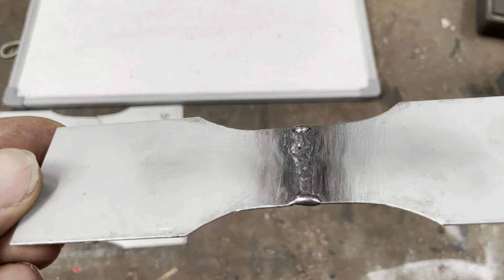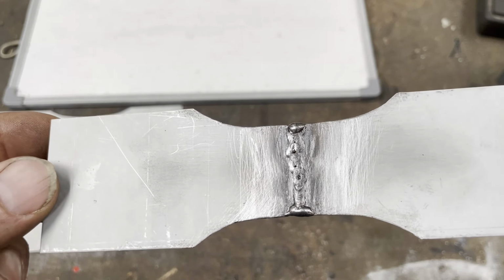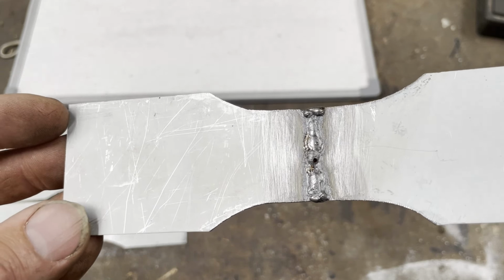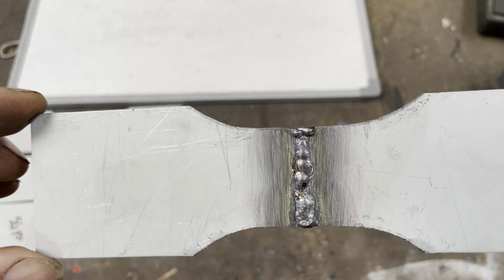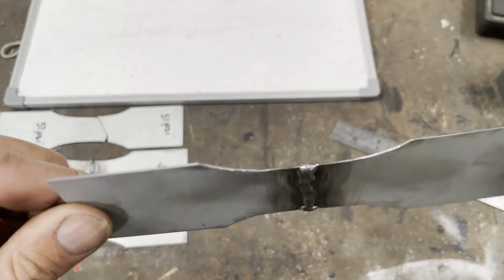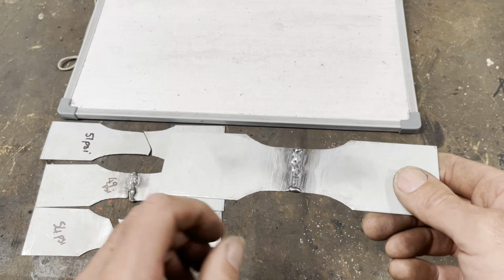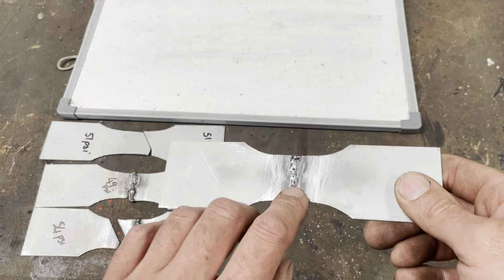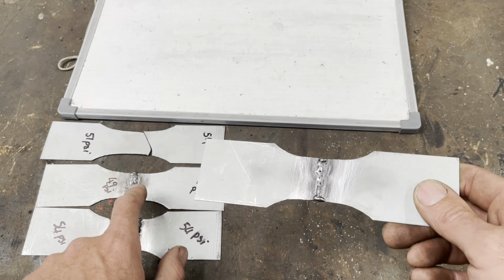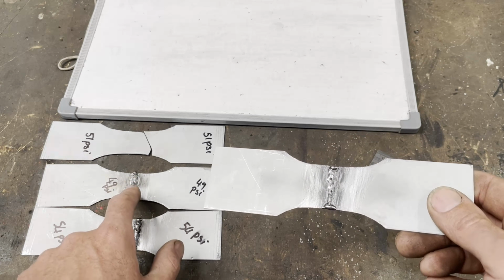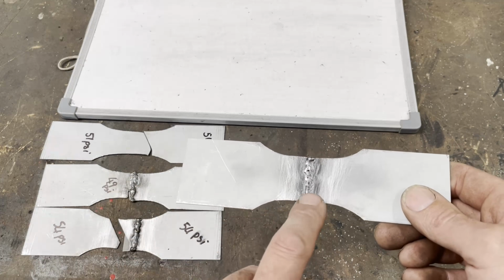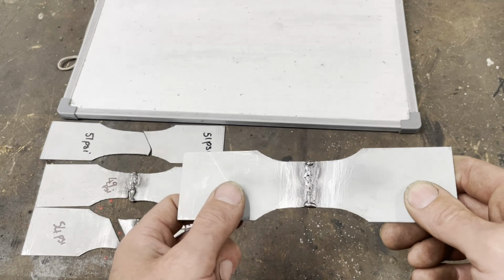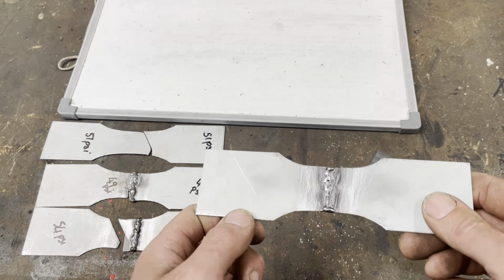Here we have TIG using filler rod. That is the front and that is the back side. So we've got good penetration on the back. I've done a video comparing the hardness of a TIG weld compared to a MIG weld, and people still think the MIG weld is a harder weld, but it's not. It uses the same filler rod, the same amount of heat. There's no difference in hardness.